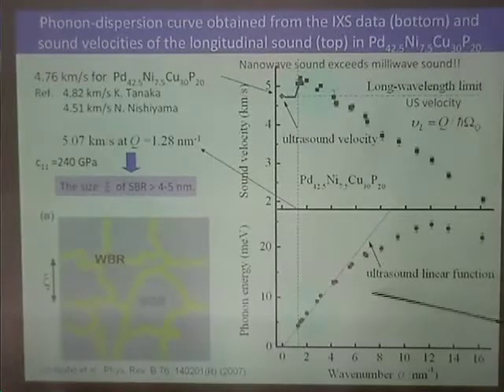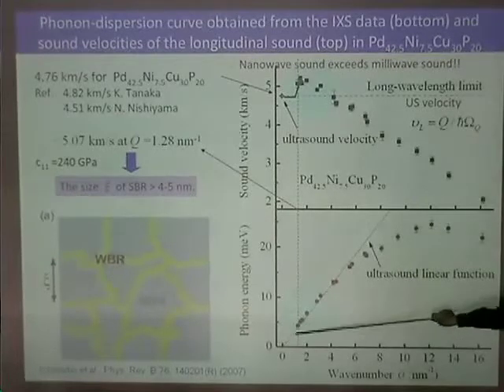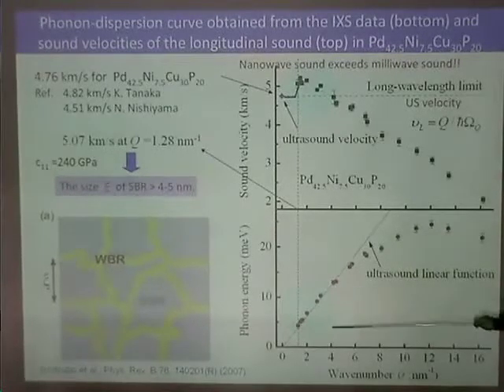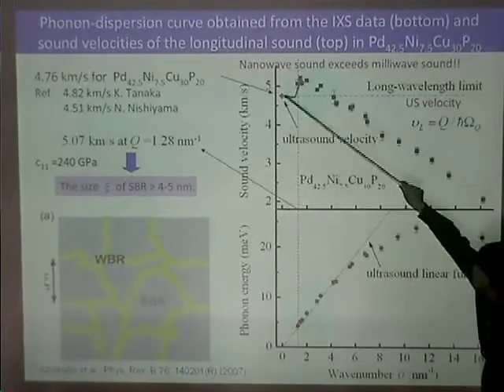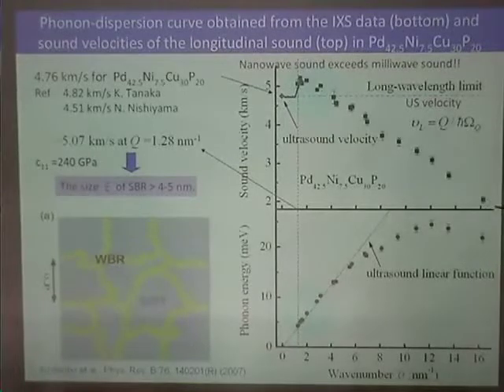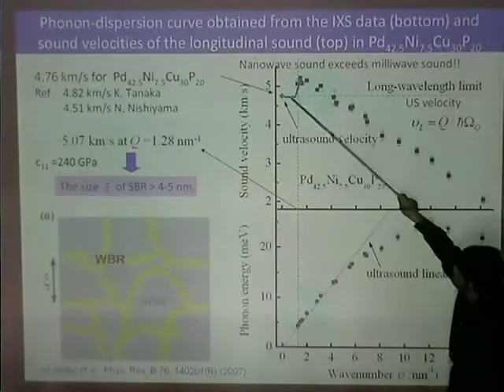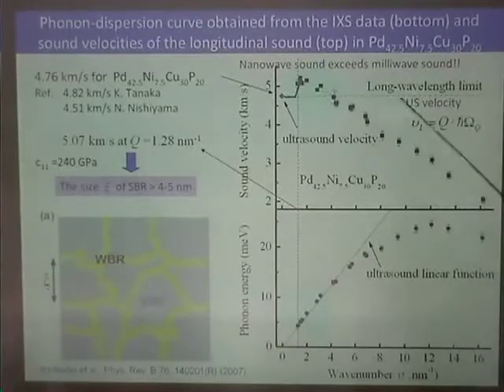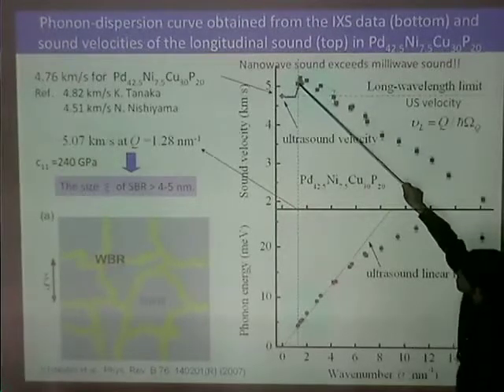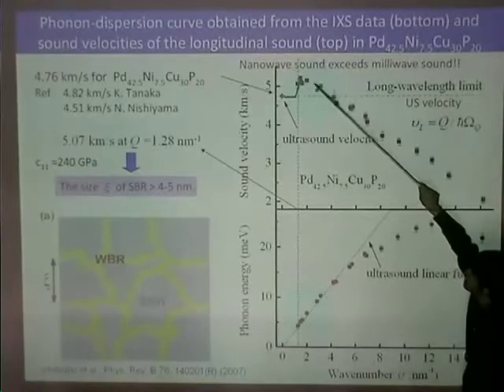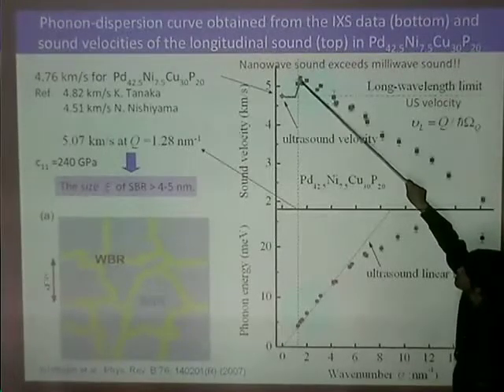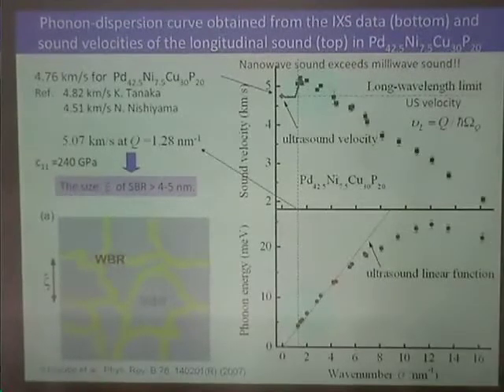So this is the phonon dispersion relation obtained for the palladium, nickel, copper, phosphorus metallic glasses. This is the ultrasound line. So please look at these regions. This is the phase velocity of the phonon versus wave number. This dashed line indicates the ultrasonic sound velocity, which is the long wavelength limit. But as you see, in some part, the sound velocity of the phonon exceeds the ultrasonic sound velocity.